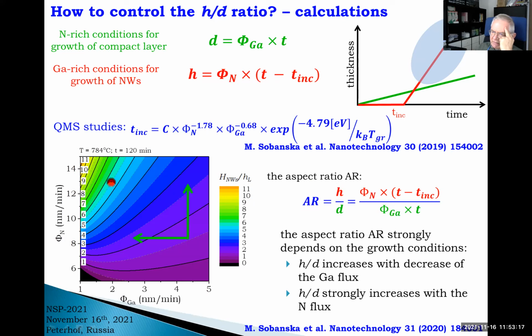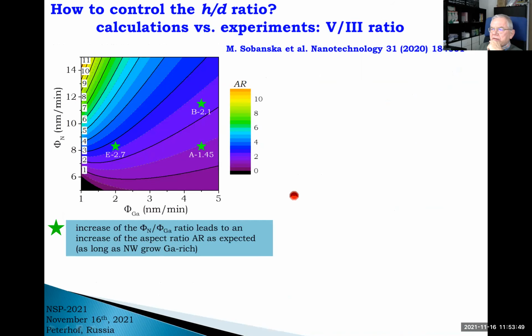Nitrogen flux, gallium flux, temperature is fixed, and these lines show calculated values of this aspect ratio. And as you see, if we want to put as much gallium into nanowires instead of the layer, we need to go to nitrogen-rich conditions. Even more nitrogen-rich conditions. We need to either increase nitrogen flux or reduce gallium flux. And how is it in practice?